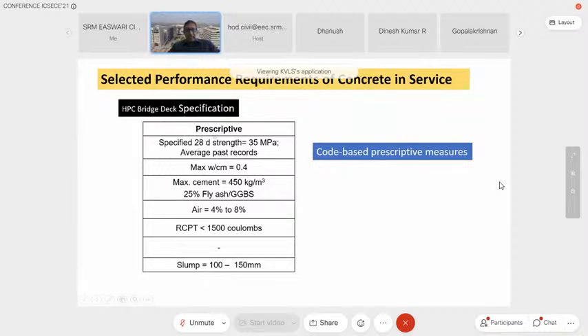in terms of strength. This is a typical high-performance concrete bridge deck specification. And in addition to that, you see here an RCPT value is prescribed. RCPT is rapid chloride penetration test value that has been prescribed, saying that the concrete that goes into this particular bridge deck should, of course, meet the strength requirement. But it should also meet this requirement of having a low chloride penetration. And that would ensure that chlorides cannot get through and steel would not corrode. And that would ensure a longer lasting bridge deck. So this is about performance-based requirement and longer lasting structure.